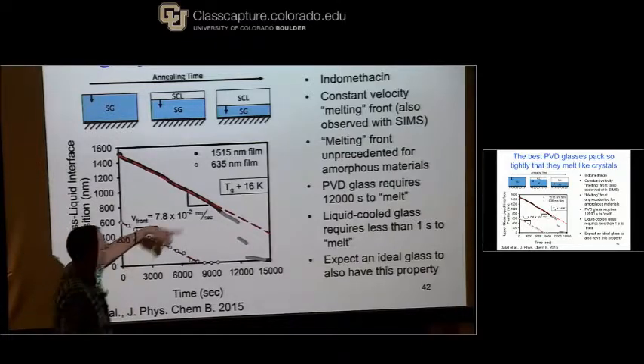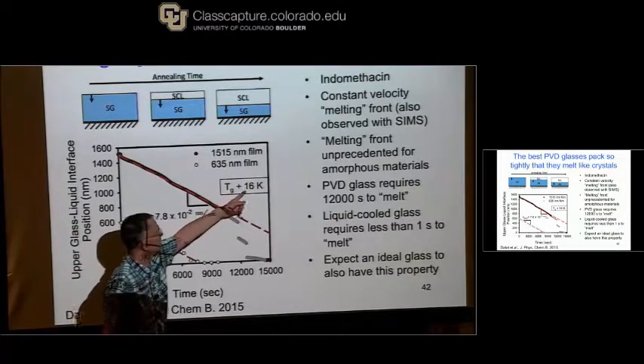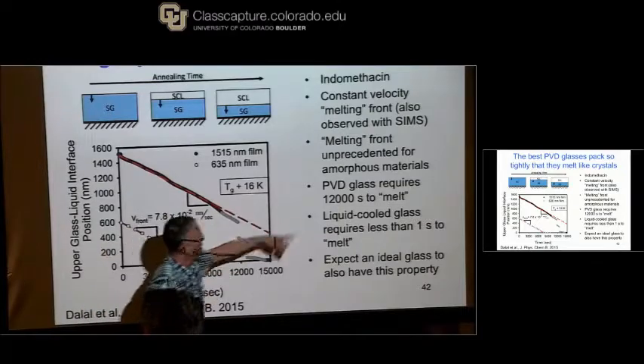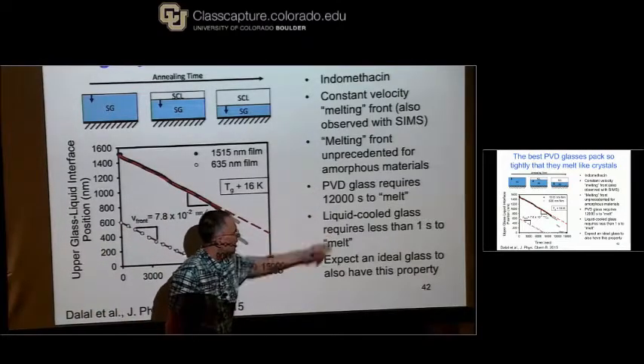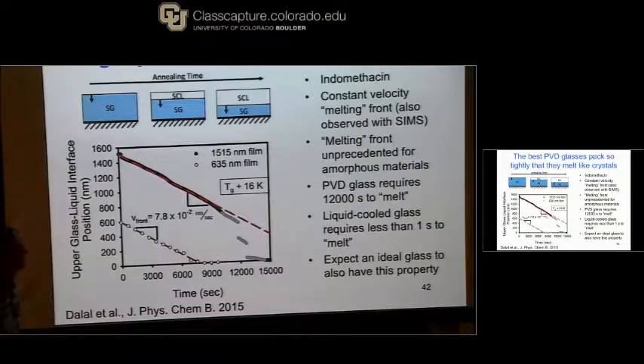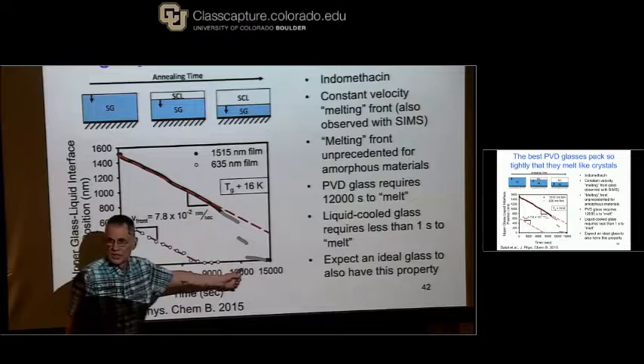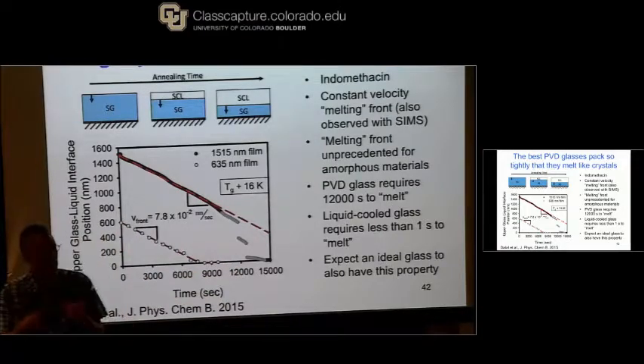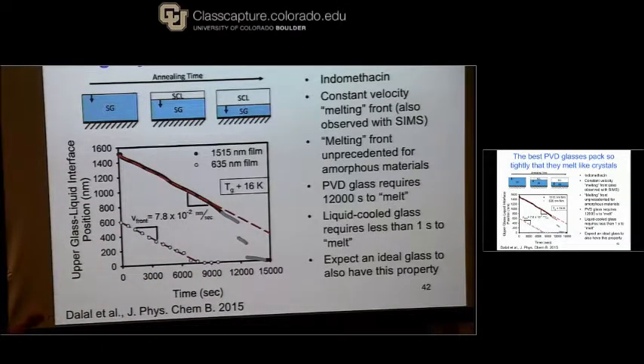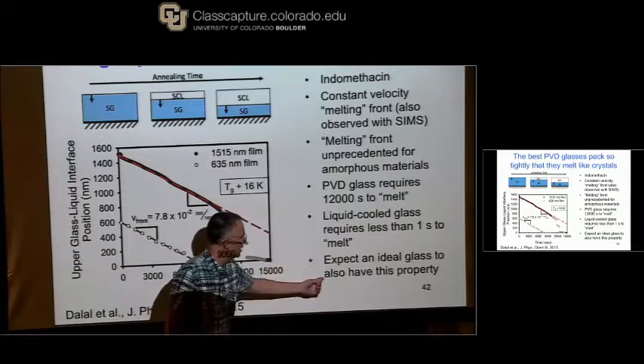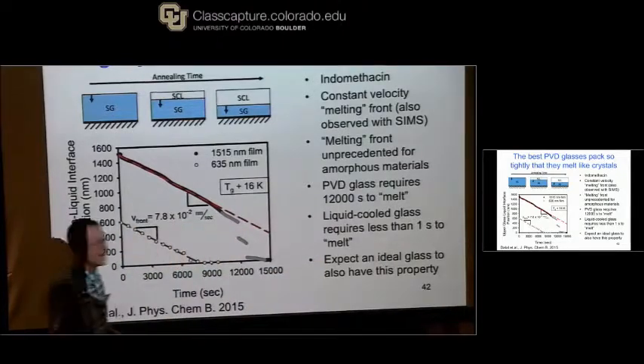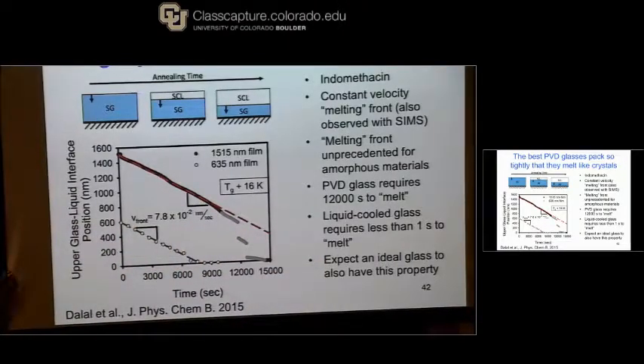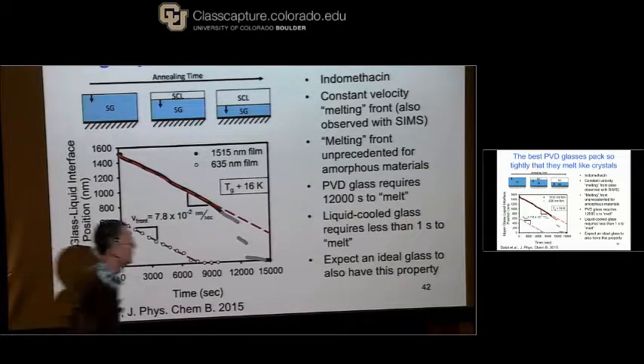This is actually at a quite high temperature, 16 Kelvin above Tg. Under these conditions, a liquid cooled glass would turn into a supercooled liquid in less than 1 second. This is taking 10 to the 4 seconds. Okay, that's just another indication of the very high barriers there are in this material. So here, I go out on a limb. I expect an ideal glass to also have this property. I think the barriers in the middle are so high compared to the surface that it's going to melt like a crystal.